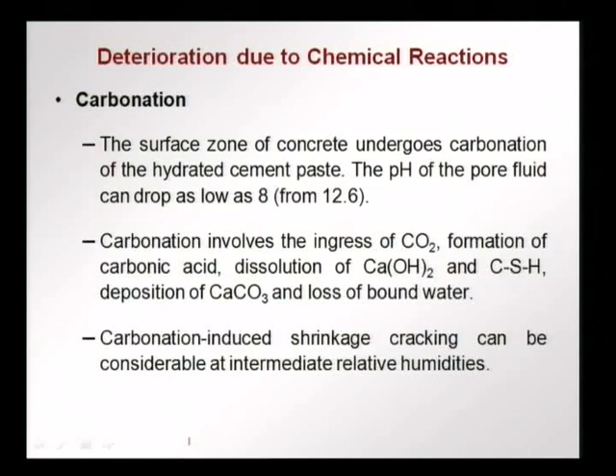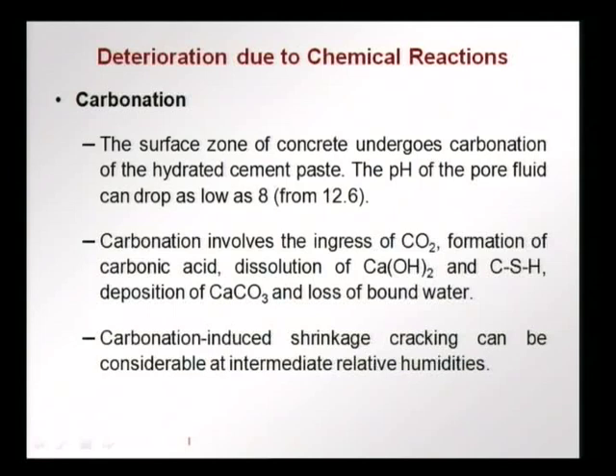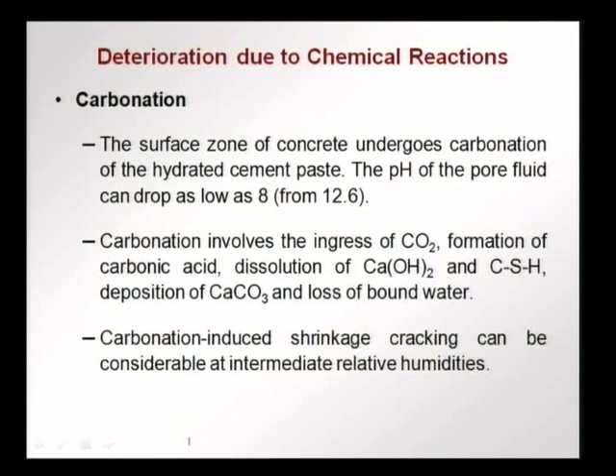Carbonation first requires the ingress of CO₂. CO₂ and water combine to give carbonic acid, which dissolves the calcium hydroxide and CSH — some is lost and the rest deposits as calcium carbonate in the voids. Some bound water is also lost, causing shrinkage. Carbonation-induced shrinkage cracking can be considerable at intermediate relative humidity, around 60%. At very low humidity, there is not enough water to facilitate carbonic acid formation; at very high humidity, pores are saturated with water, blocking CO₂ entry.